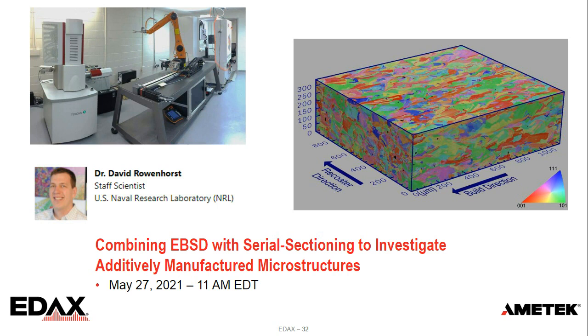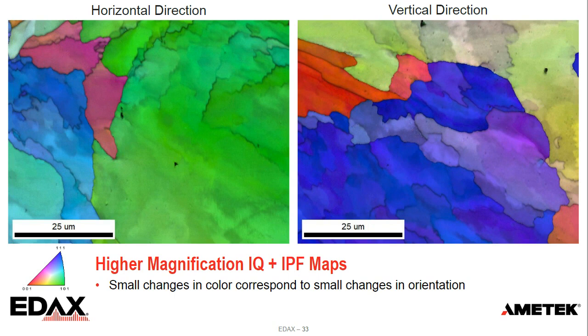In my work, I was starting to look, it's still in progress, at the structure at higher spatial resolutions. So here we're looking at an area where we can see within some of the grains that the color changes. There are small changes within a primary color, and that represents small changes in the misorientation.